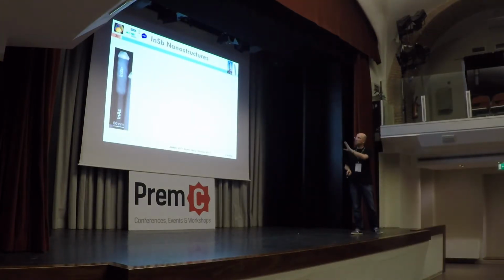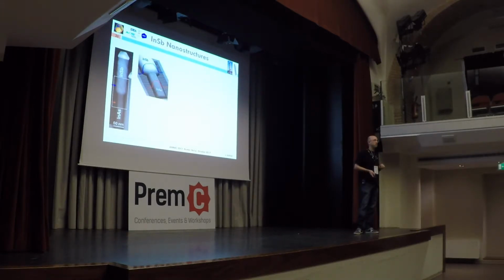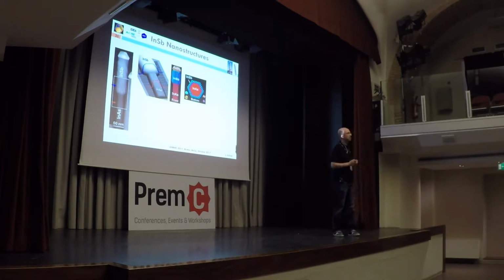So first of all, let me explain how we grow these really nice indium antimonide nanowires. Indium antimonide is a really interesting material because it has a low band gap, so it's good for these low energy or low power consumption electronics, but it's also really interesting because it has a really huge mobility. So the material is very interesting, but anytime that people have tried to grow indium antimonide on top of indium arsenide substrate, the problem is that there is a strong mismatch and a lot of misfit dislocations are created. These misfit dislocations are propagating along the material and they destroy completely the mobility that it should have, or at least the mobility that it has been calculated in the bulk.